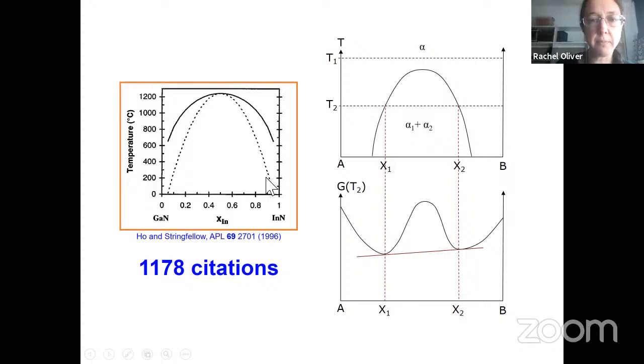Now, there's also this dotted line on the phase diagram. What is that telling us? Well, within this curve, which has this kind of cubic form with the two minima, there are 2 points of inflection, where d2G by dx squared, the double derivative of the energy with composition, is 0. And if we think about compositions that are between those 2 points, like my composition x dashed here, if my single phase alloy, my alpha, had composition X dash, it would have a high energy, okay? And it could get to a lower energy by splitting up into compositions X1 and X2.